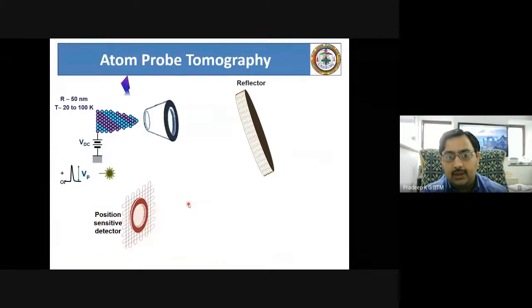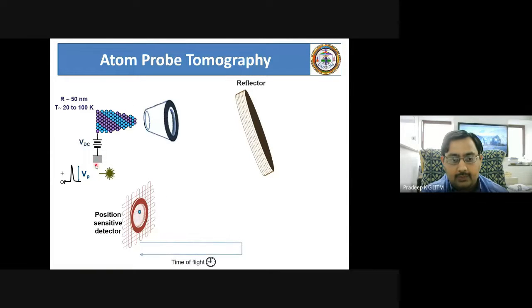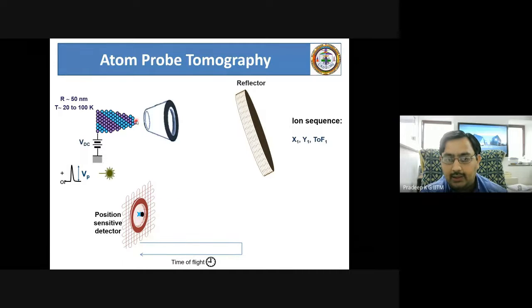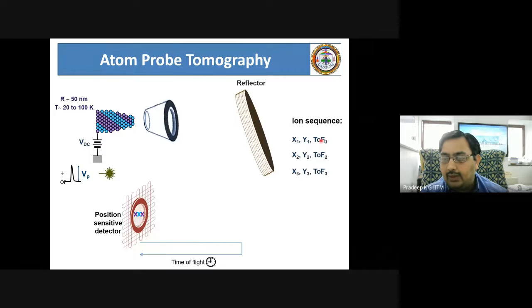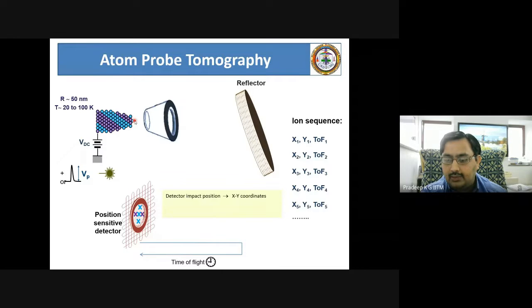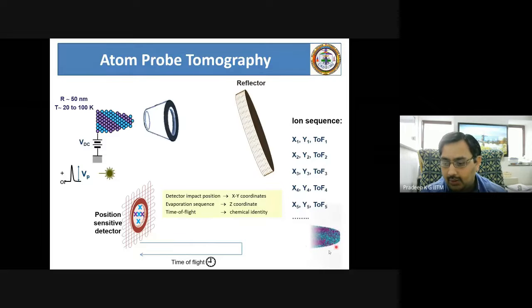So if I now show you the schematic of how this entire microscope works, you are applying positive potential to a sharp needle and activating the pulsing, so that the triggering of the pulse starts the timer to measure the time of flight over which the ion travels this fixed distance. You can therefore get the coordinates of detection in the detector as x and y, and the time of flight, which is the time taken by each individual atom to reach the detector from the material. So when you measure all this information, these 3 different numbers are good enough to reconstruct all the lost material out of your sharp needle into a more representative 3-dimensional volume as what you see here.